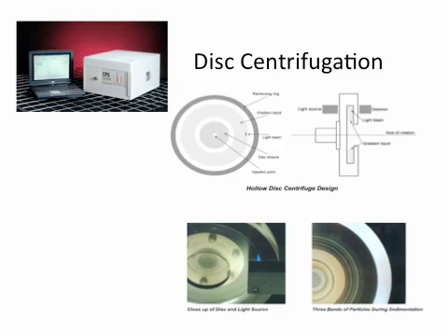So you can separate particles on size, but also on shape, because rod-like particles have a different way of being exposed to a gravitational field than spherical particles have. It's quite a nice toy, and you can separate silica particles of 20 nanometers fine. Gold works pretty well down to 5. Obviously, the density difference is really important, right? If there's a density match, you won't separate anything at all. If the particles are lighter, you use the inverse. You inject the particles on the outside, and then they move towards the middle.